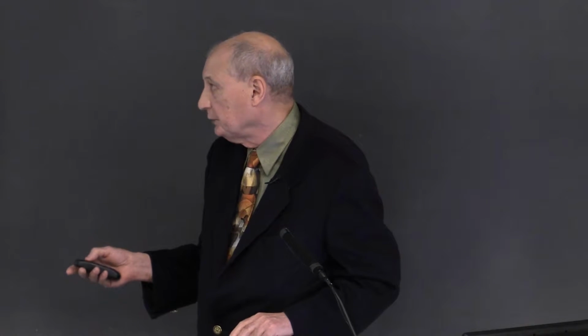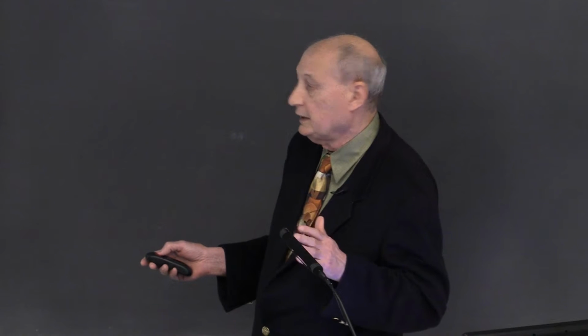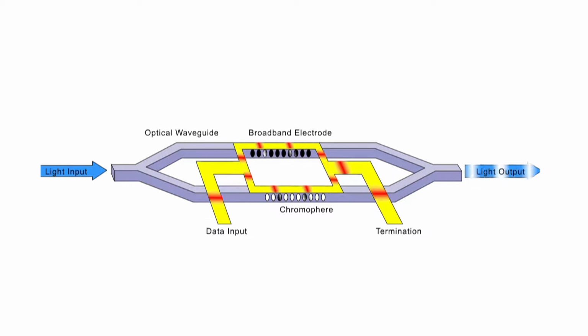And if you, for example, take these materials and you induce alignment by electric field poling, you apply an electric field to the material when it's near its glass transition temperature, you can align chromophores in one arm of this device called a Mach-Zehnder interferometer in this direction, and you can apply a poling field in the opposite direction to align molecules here. When an electrical signal comes in, if the magnitude is such to produce a forward phase shift of 90 degrees in this arm and a retarding phase shift of 90 degrees in this arm, the two optical signals will be 180 degrees out of phase and light will be turned off. So what happens is that you transduce this electrical signal onto this optical transmission as an amplitude modulation.